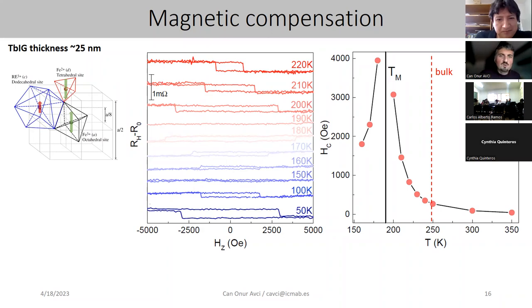So I did not explain very much in detail, but these are not the magnetization data, but rather the Hall effect data. So the Hall effect data has another anomaly in these films that is independent of the magnetic compensation, that it also changes sign at a certain temperature. So there is a sign reversal. So basically, there are two things happening here.